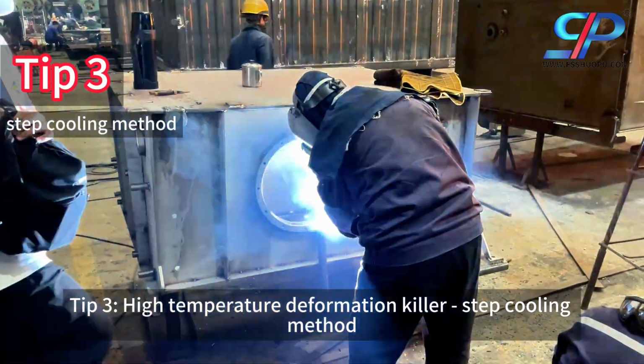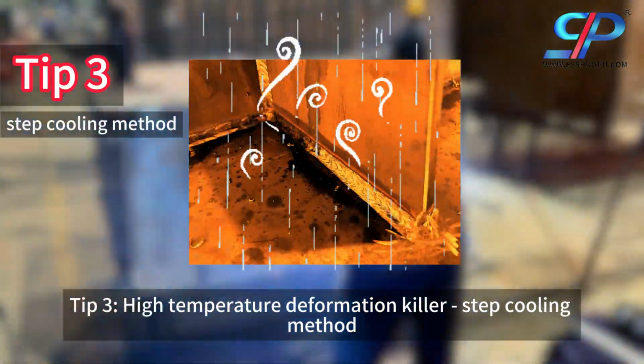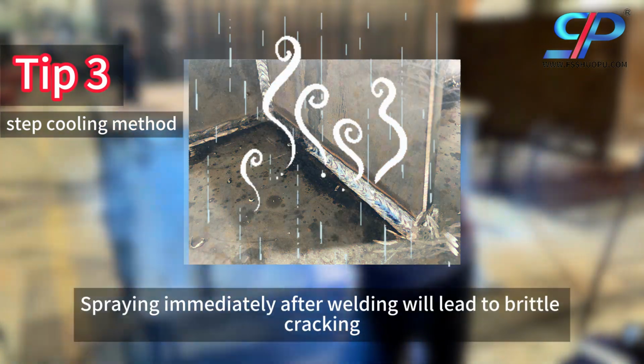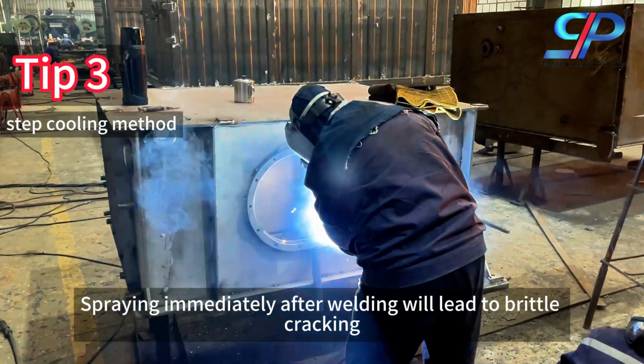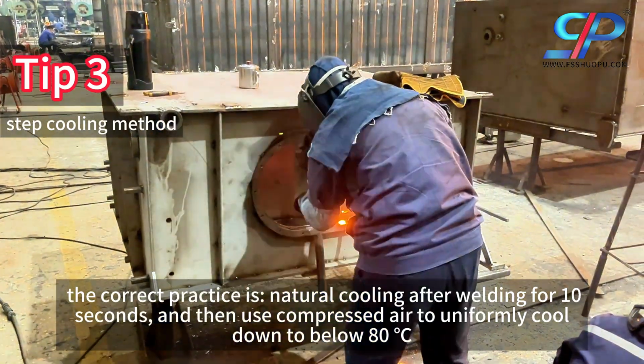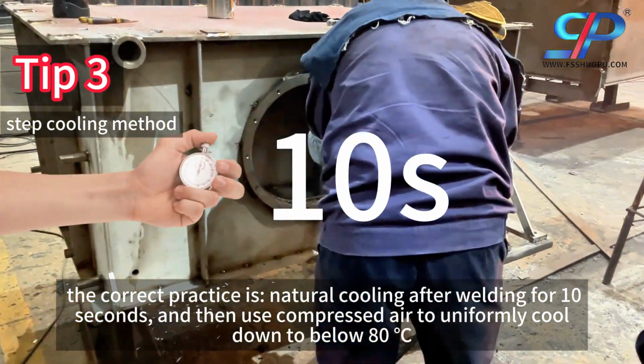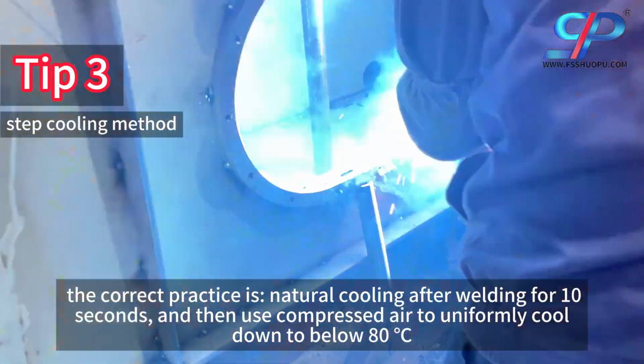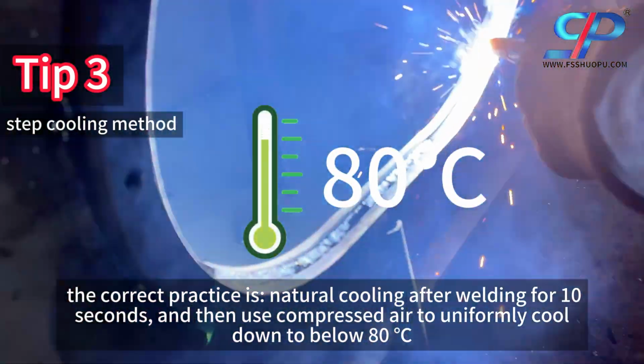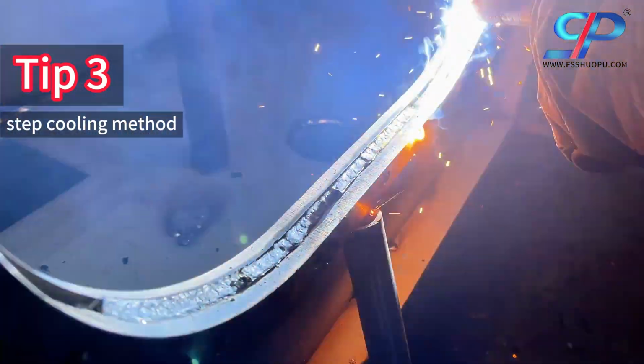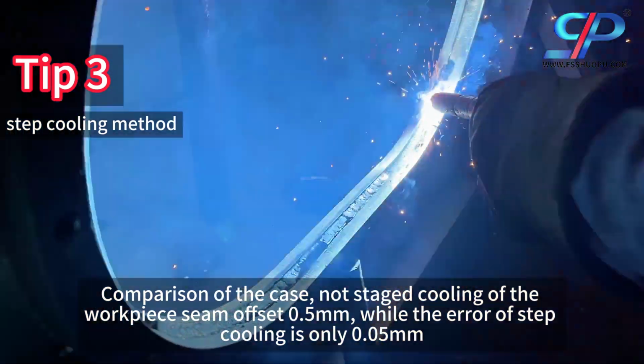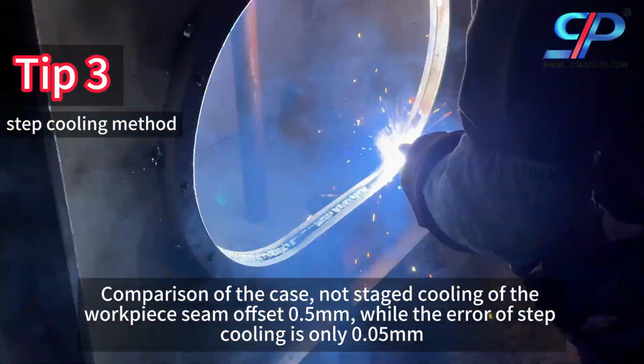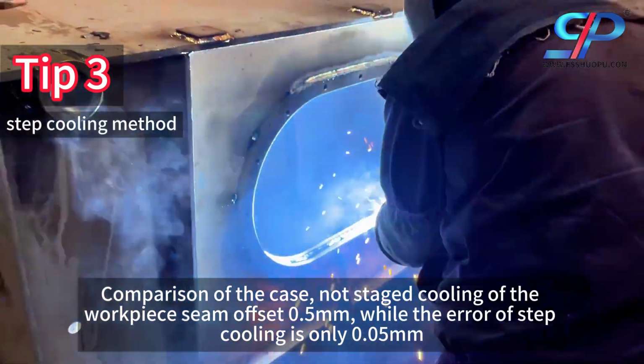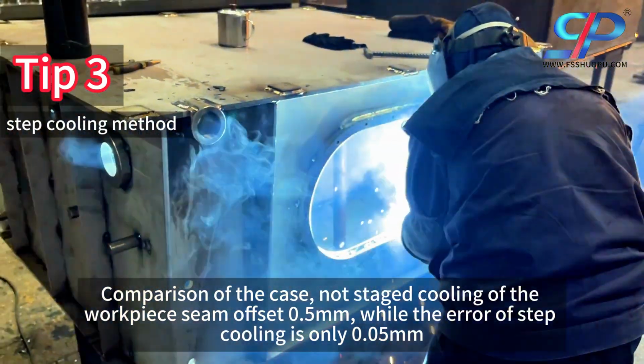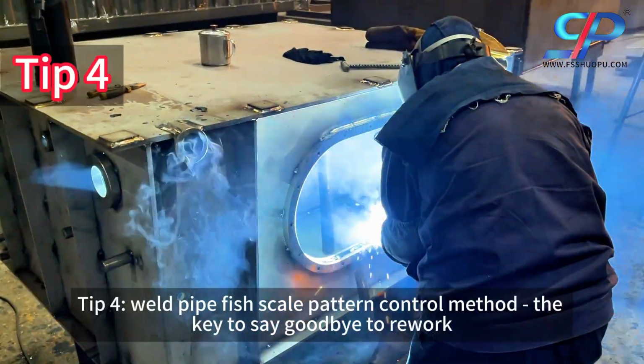Tip 3. High temperature deformation killer: the step cooling method. Spraying immediately after welding will lead to brittle cracking. The correct practice is natural cooling for 10 seconds after welding, and then using compressed air to uniformly cool down to below 80 degrees Celsius. Comparison of the case: without staged cooling, the workpiece seam offset is 0.5 millimeters, while the error with step cooling is only 0.05 millimeters.